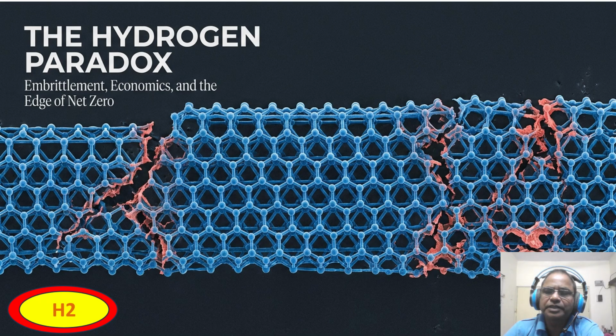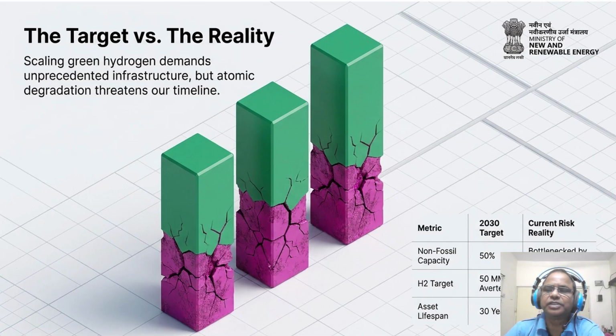So, coming to our target versus reality. On this slide, you can see three isometric bars representing our 2030 vision versus the current risk landscape. So we can see the green segment represents our targets, a 50% non-fossil capacity, and 50 million metric tons of CO2 averted annually. However, look at the magenta crack at the base of this bar. Our current risk reality shows that while we target a 30-year asset lifespan for hydrogen infrastructure, embrittlement is threatening